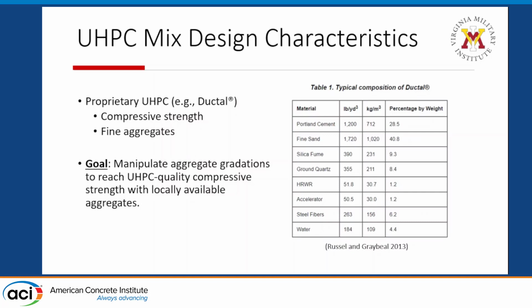The proportions that you see on this slide from Table 1 are Lafarge's Ductal UHPC. Lafarge's Ductal UHPC was able to reach a 30 KSI cubic compressive strength. They have a lot of reasons that they're able to reach this strength, like a really low water cement ratio. They used oven curing and fine aggregates, and we chose to focus on the fine aggregates as a big reason why the Ductal UHPC was able to reach a 30 KSI compressive strength, much higher than the bare minimum for UHPC of 21.7 KSI.